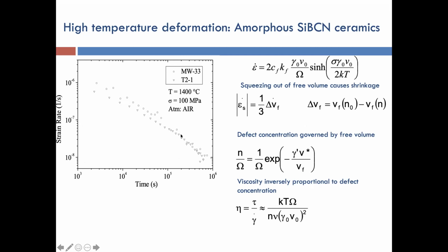And of course, the physics part is shown here on the right-hand side, where we say that the continuous decrease in the strain rate is primarily because of the squeezing out of the free volume in these materials. And we show how strain rate is a function of the defect concentration and so on.